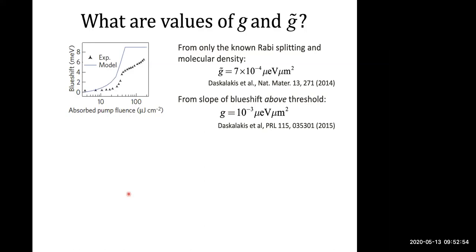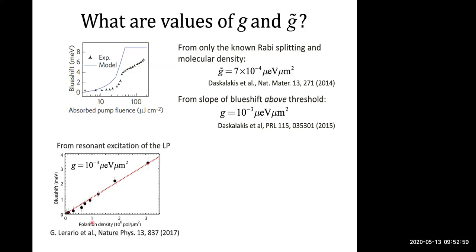And we can also estimate this value of G in a completely different way. What you could do is resonantly pump one of these lower polariton states without populating your dark states, and then just look at the blue shift of that lower polariton resonance as a function of pump power. And from this sort of measurement, you also obtain a G of about 10 to the minus 3 micro eV micron squared. So all of these values are relatively consistent.